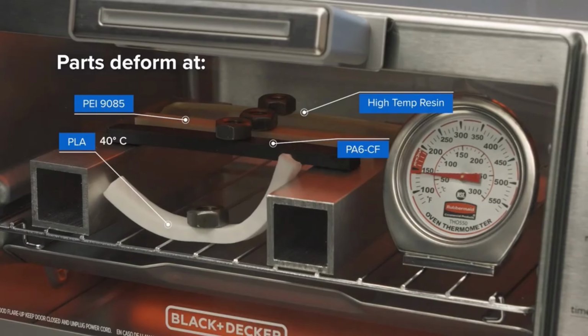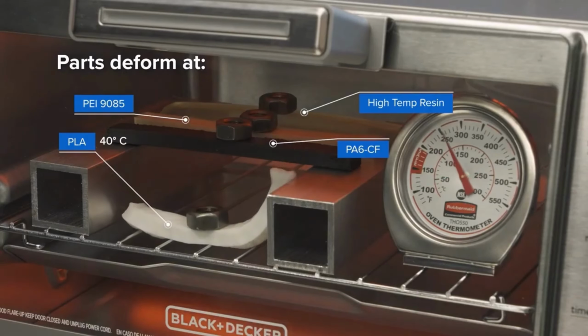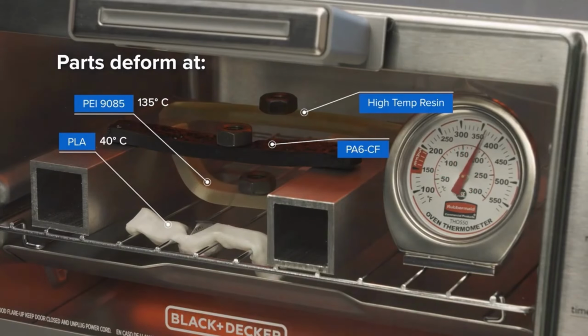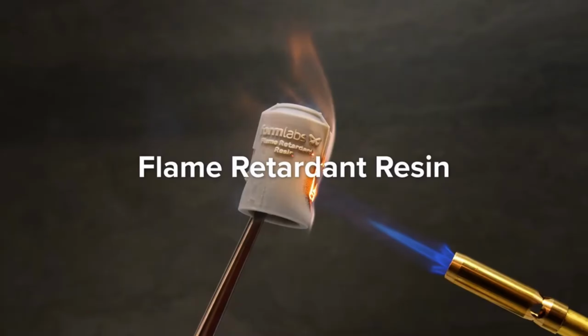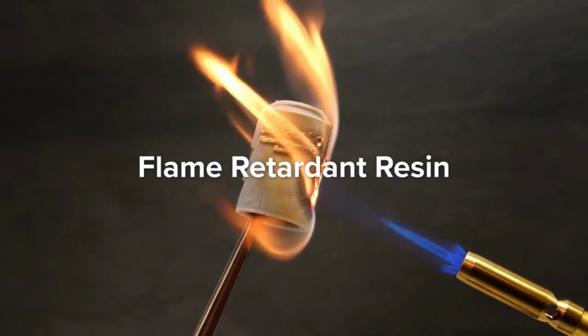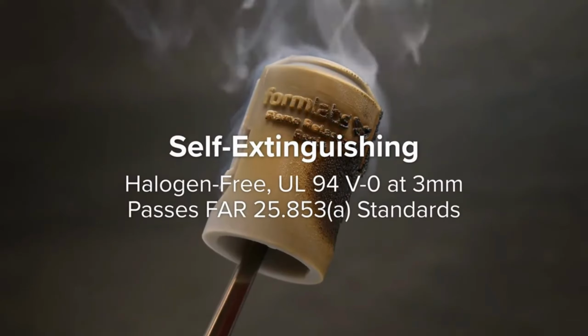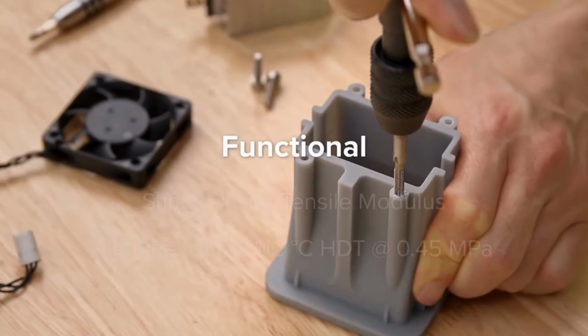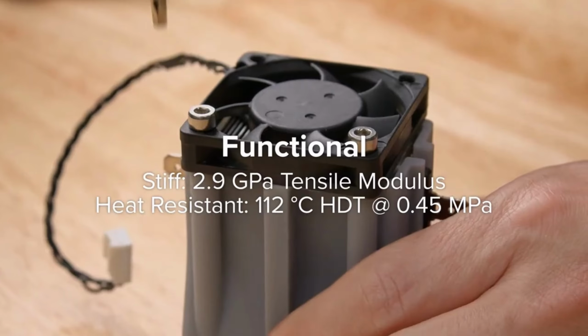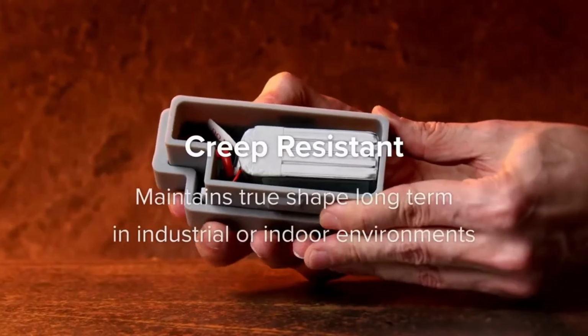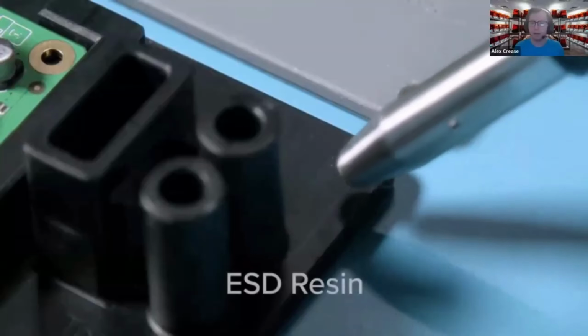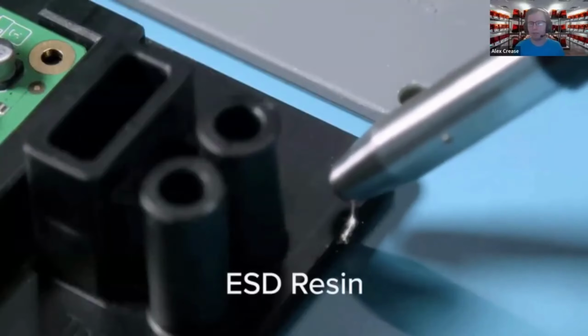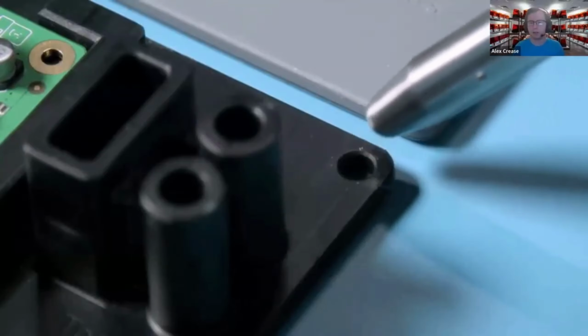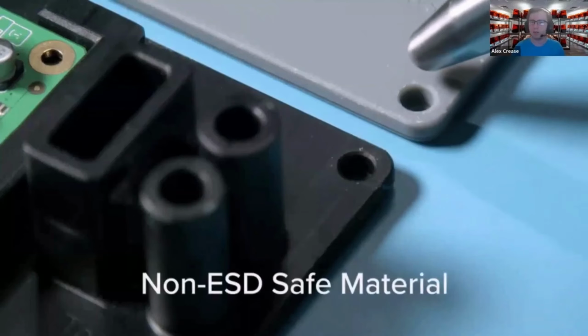High temp is a heat-resistant resin thanks to its heat deflection temperature of 238 degrees Celsius. Flame retardant resin, or FR, is a UL94 V0 rated material, meaning a 3 millimeter thick test sample self-extinguishes within 10 seconds of ignition. And ESD resin is a static dissipative material with modulus and impact resistance similar to ABS.